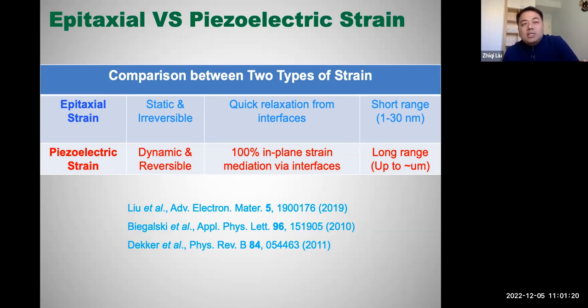For example, their disadvantage is that it's very difficult to control and manipulate the spins of collinear antiferromagnets. I think piezoelectric strain is an effective one, but you can also use external magnetic fields. But once you can realize a memory device based on the collinear antiferromagnet, then the information is very safe, in terms of stability against external magnetic fields. Actually, the zero stray field is the advantage for collinear antiferromagnets, and also the disadvantage for storing information, since it is hard to easily control the spins in the collinear one.